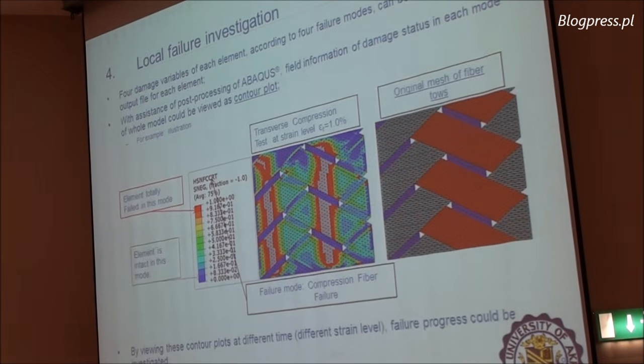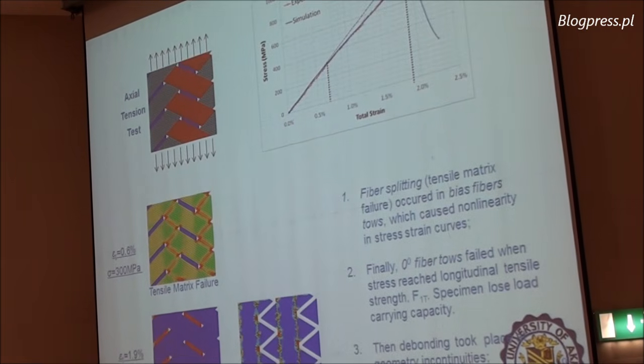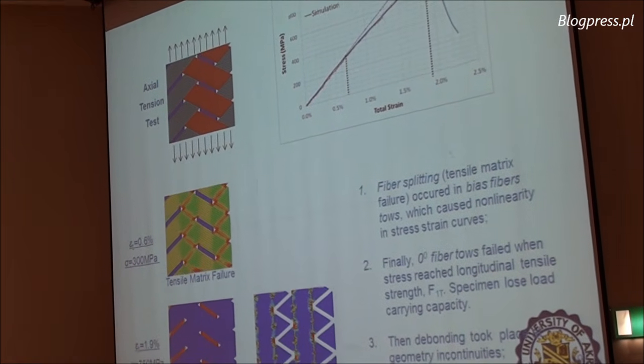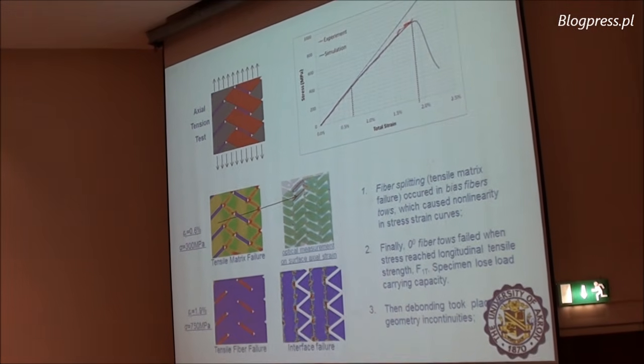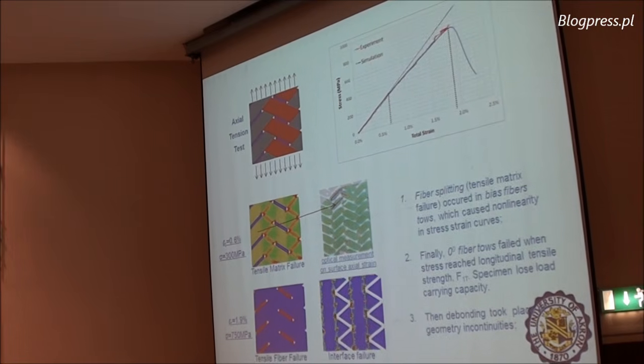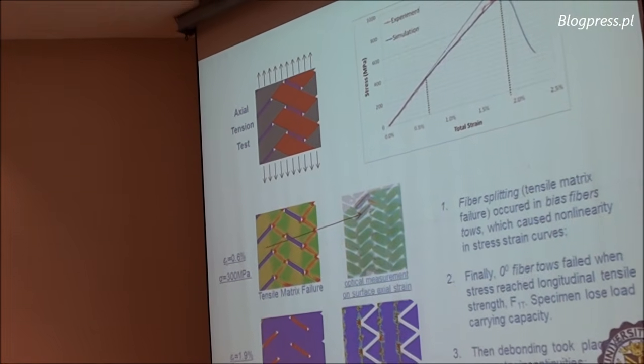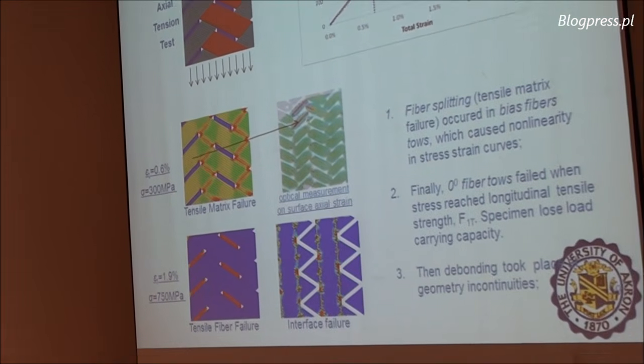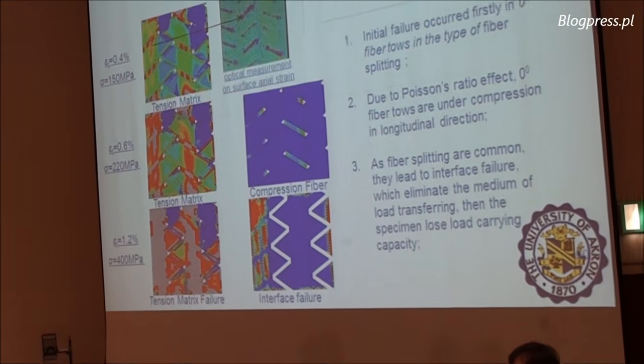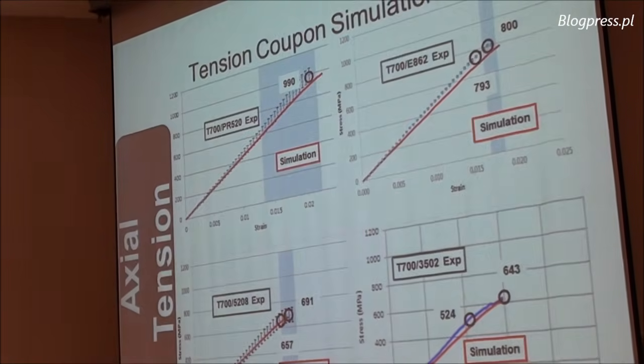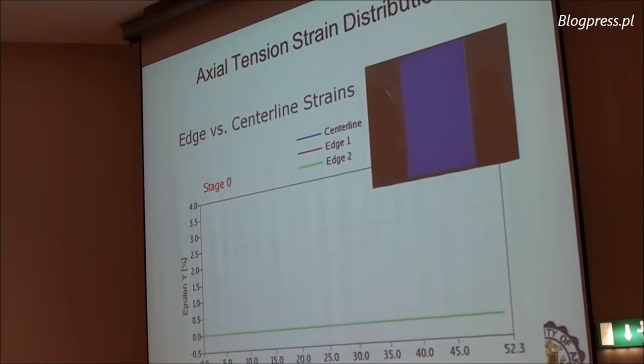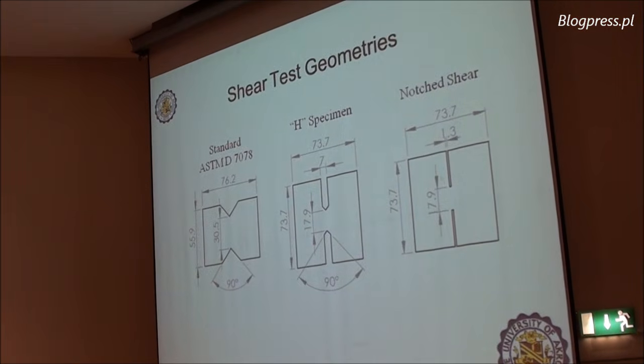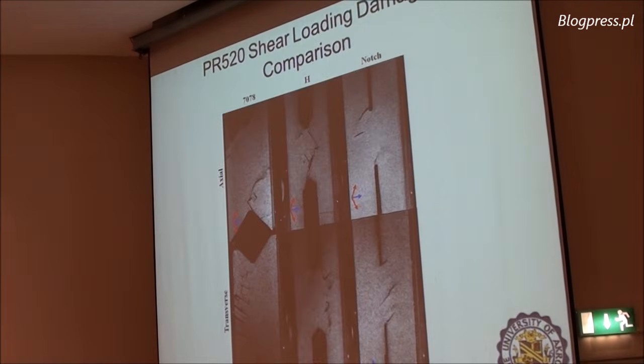And also you can look into the analysis and try to understand if you capture not only the slope of the stress-strain relationship, but also the damage. This is the simulation on the left and the experiment on the right, which really indeed captures those failures that occur in the material itself, and again other tests are shown here. You do the same thing for the macromechanical model, and eventually you can get the tests and samples that give good results.